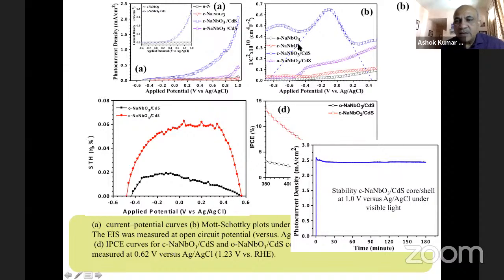slopes of these plots. So you can see that in the blue one, you have a positive slope as well as a negative slope, right? Whereas in the orthorhombic system, you have only one slope, okay? So it tells you what kind of charge carriers are present. Are they holes? Are they electrons? It also tells you how the photocurrent is. So you see, the one which has the cubic crystal system has higher photocurrent, right? Whereas the other one has a lower photocurrent.